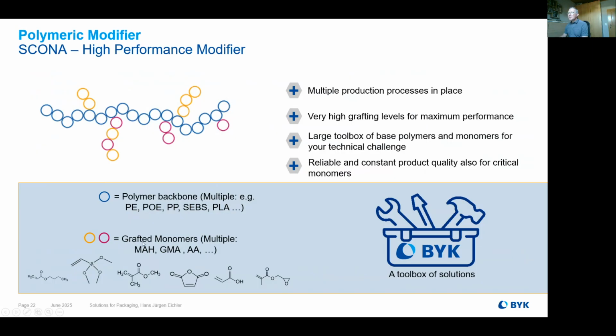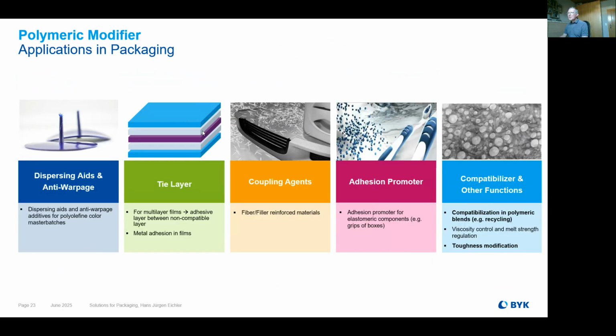And what we are doing is playing around with a grafted monomer. So we have maleic anhydride, we can replace it with an epoxy, we can replace it with an acrylic acid. All this should be shown here with these yellow or red ones. It's just a simple toolbox, I would say, but very efficient, especially if you want to improve properties in your plastic applications. And here you get now an idea what these polymeric modifiers are able to do.